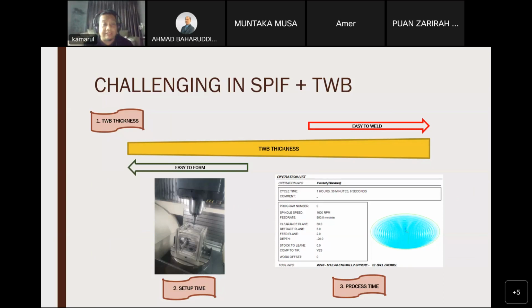The third one is the process time of the SPIF itself, because previous SPIF work normally uses a CNC machine or robotic arm with a very thin sheet of metal, sometimes 1 mm or less, so it's easy to form. Then there's no issue for a fast or quick process. But when we use a tailor blank of 1.5 mm and welded, it's not easy to form at high speed, because like I said just now, I already tried several parameter combinations. After so many failures, I had to adjust the parameters again and again, which means slowing down the step size and the feed rate, so the processing time expands.